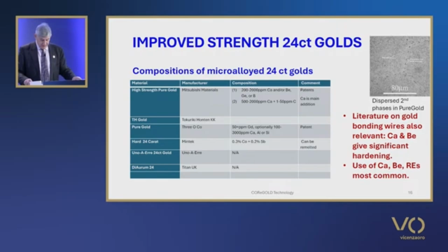The 3O Company patent indicates that the pure gold material contains 99.7% gold plus 50 or more parts per million of gadolinium and optionally 100 to 3,000 parts per million of calcium, aluminium or silicon. In a patent from Tokuriki Honten KK in Japan, an alloy for precision casting is claimed containing small amounts of hafnium and the rare earths.